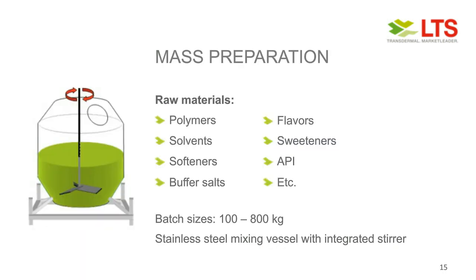So it can be as easy as it looks here, starting with the vessels, which can contain batch sizes between 100 and 800 kilograms, even be larger if possible. For example, sometimes we're looking at a few thousand kilograms, which we have produced. We can add just all the raw materials, polymers, flavors, solvents, etc., within this vessel and just mix it, if it's to achieve a homogeneous polymer solution.